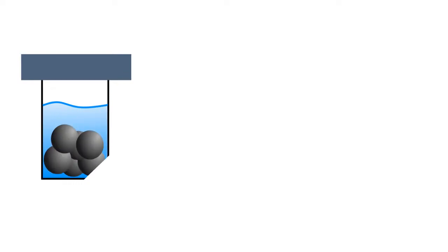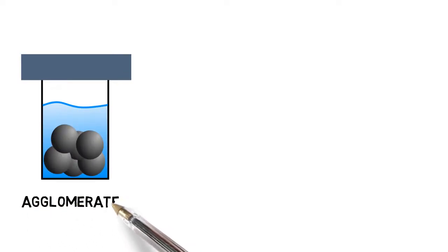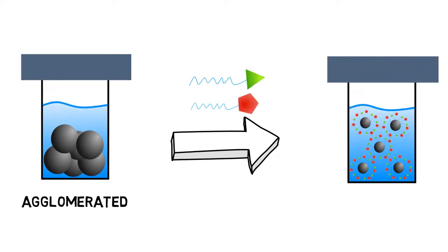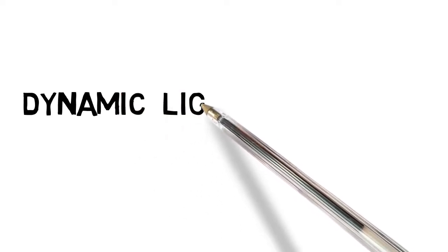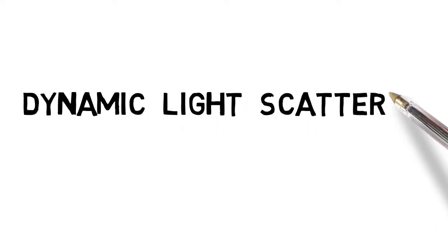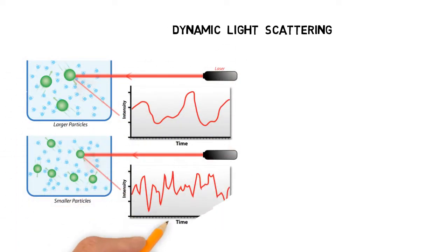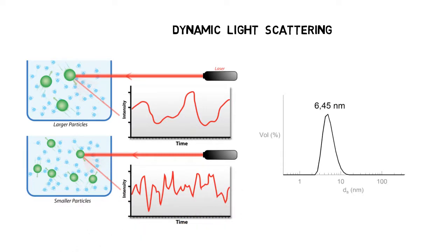I mentioned before that it's possible to allow your solids to behave as large molecules in solvents. By making specific molecules bind on the nanocrystal surface, you cause the nanocrystals to repel each other. This way, they don't clump together anymore and you get a stable colloid. To determine if the particles aren't agglomerated, a technique called dynamic light scattering can be used. To put it briefly, a laser emits light into the colloid, and based on the scattering of this light by the suspended particles, you can gain information about the particle sizes in suspension.